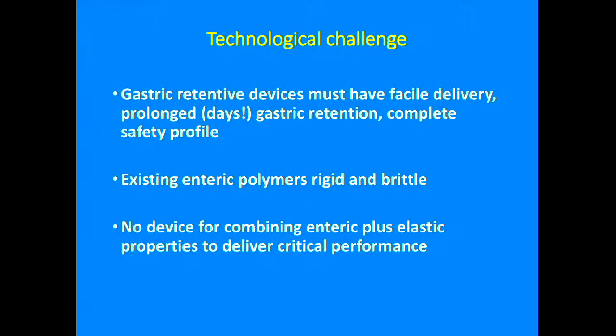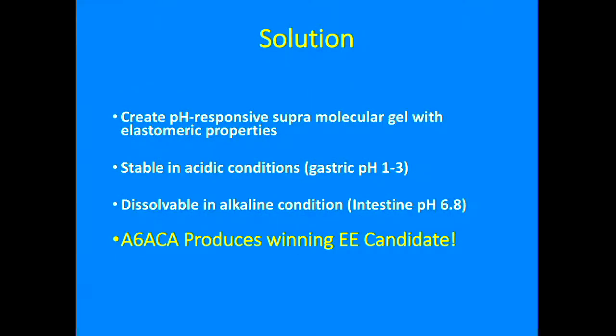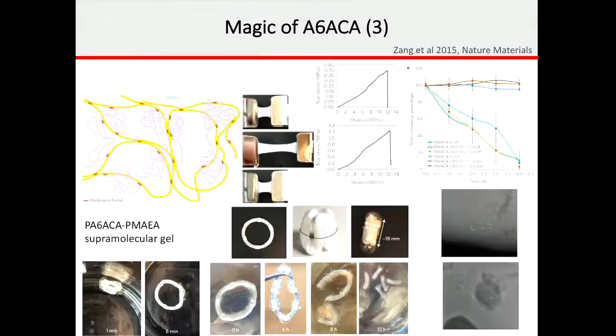So gastric retentive devices must have facile delivery for prolonged days of gastric retention. And the existing enteric polymers were rigid and brittle, so there was a big challenge. And there was no device combining enteric plus elastic properties. So they found a solution. They said, why don't we create a pH-responsive supramolecular gel, stable in acidic condition, gastric pH, but dissolvable in alkaline condition. And you know finally who the winner was? A6-ACA. They created this supramolecular gel, as you can see here, with polymethacrylic acid-co-ethyl acrylate as a copolymer.